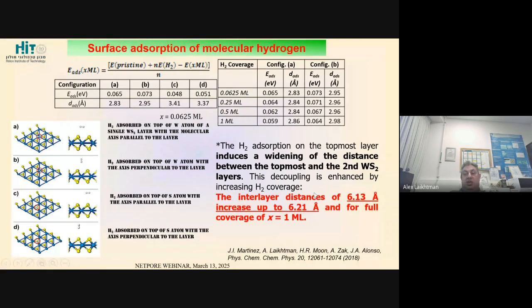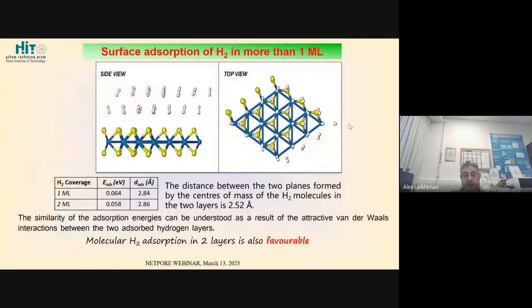But then we noticed one additional effect, which later proved to be very important for us. When we have this hydrogen adsorption, which is energetically favorable, we also have some minor increase in the interlayer distance between WS2 layers, because, as you know, it's a multi-layer structure, from just 6.13 angstroms for pristine nanotubes to 6.21 for the hydrogen adsorbed nanotubes. You can consider it's very minor, and there is no sense, but later we proved that it saves us a lot of energy. Later, we also proved that hydrogen can be adsorbed in several layers, in multi-layers, and still the adsorption process is quite favorable. So we can have 2 or 3 layers of hydrogen. This shows why we have quite high hydrogen percentage on the nanotubes than it could be in the case of